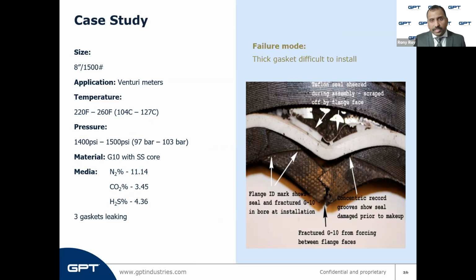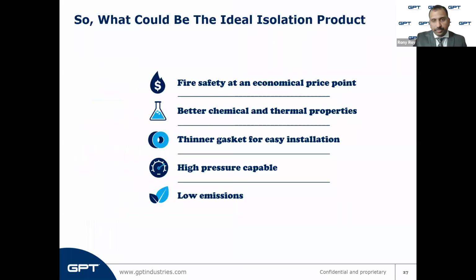Most high pressure isolation gaskets have retainers that are at least 6.6 mm thick. They typically have a seal that protrudes approximately 5 mm more, and so a flange gap of at least 9 mm is necessary so as not to damage the seal or gasket. Interestingly, with this case, the downstream gaskets appear to have been installed first, and all 3 functioned properly. But when the upstream gaskets were installed, the space was very tight and limited, and that led to the tearing of the GRE as well as the popping out of the PTFE's additional seals.